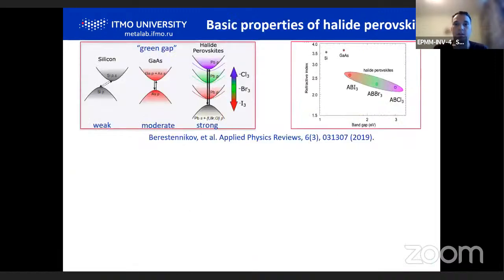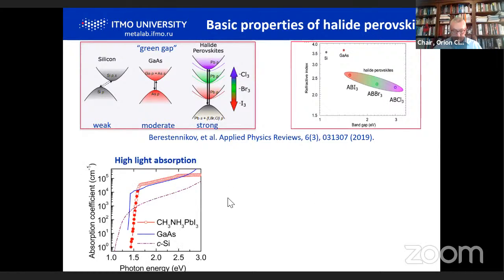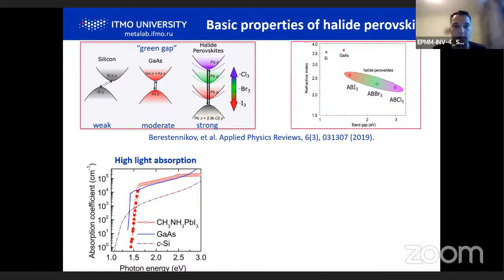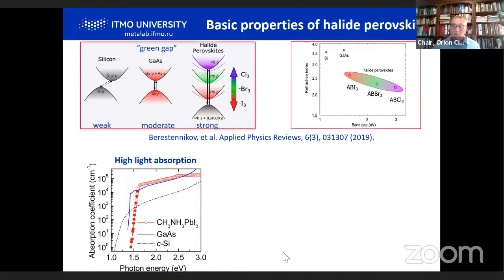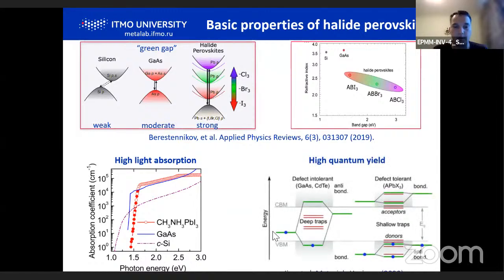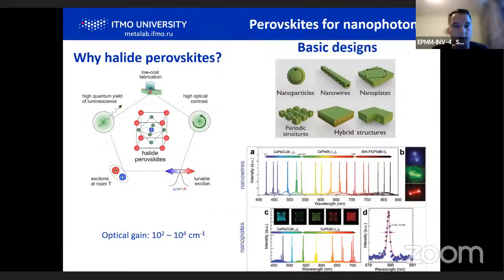So what are the basic properties of halide perovskites? First of all, it's a direct band gap material with a tunable band gap by replacement of halides at the very end of the formula. Their interband transition is stronger even than for gallium arsenide. Also, this is a mid-refractive index material with a refractive index between 2 and 3, which is higher than for polymers, and we can provide a good contrast for nanostructures made of these materials. These materials have high absorption, even better than gallium arsenide, but we normally use epitaxy-free methods, so it's much cheaper. Also the light emitting properties are very nice, because this is a so-called defect-tolerant material, very robust to formation of defects in the structure, allowing it to preserve light emitting properties.